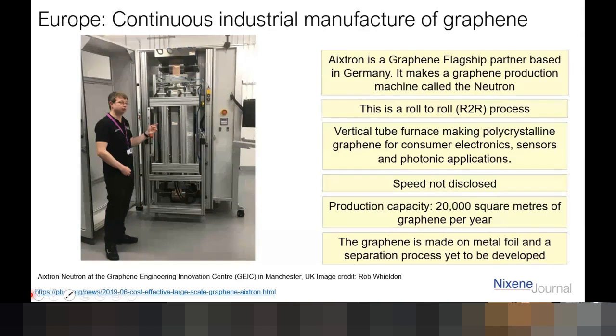So this is a graphene machine. This is at the GEIC, the Graphene Engineering Innovation Centre in Manchester. The Graphene Flagship have supported a machine called the Neutron, made by a company called Aixtron in Germany. And you can just see at the top of it, inside that cabinet, a roller and a strip of copper coming down from it. That copper foil is going down through a vertical tube furnace and then reeling up at the bottom underneath. As it goes through the tube furnace, methane, argon, hydrogen, and a few other gases are mixed in at high temperature, taken up to about 1,000 degrees. That's a roll-to-roll process for making graphene already. It can make 20,000 square meters of graphene per year. We don't know how fast it will go, but this machine already makes graphene.